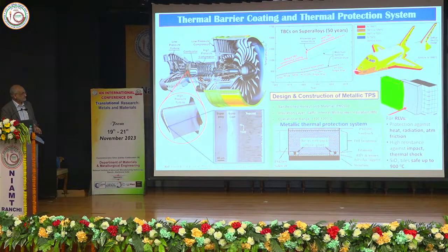These red lines, as you can see, experience temperatures in excess of 1500, maybe 2000 degrees or so. To protect these regions, you won't use metal unless you can afford tungsten or tantalum. But density-wise, they are the worst candidates for any flying object, very high density. So you'd like to go for things which are lightweight and can withstand such high temperature, so you go for alumina, zirconia, or one of these refractory oxides.